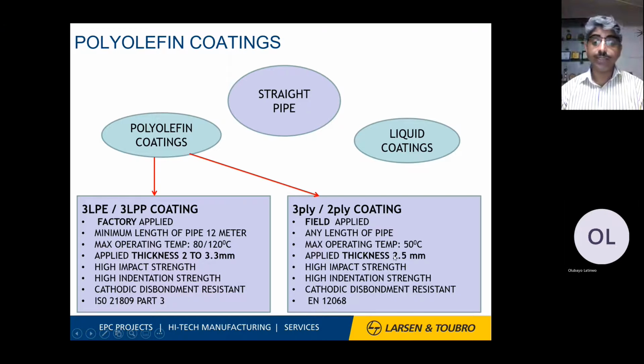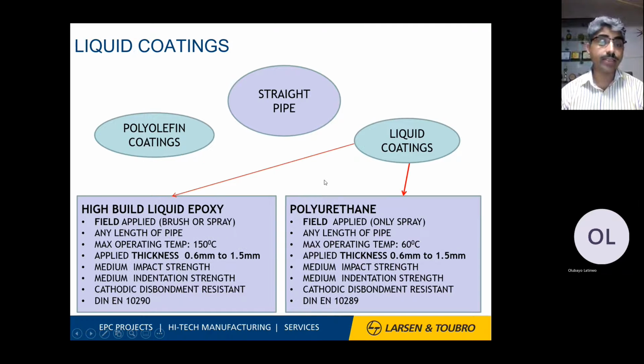This can be used up to 120. The field applied one has a restriction of 50 degrees centigrade. Normally it is for buried applications. The thickness range is 2 to 3.3 mm based on the application. Good impact resistance, because it has good impact for site conditions. High indentation strength because of laying down the pipes. Cathodic disbondment resistance because of the cathodic protection requirements. It can be read in ISO 21809 part 3 for 3LPE and 3LPP coating, and in the same way EN 12068 for 3-ply and 2-ply coatings. So these are the standards which tell you in detail about the coating, and you can read and get the information. You can reach out to me if you have any questions.